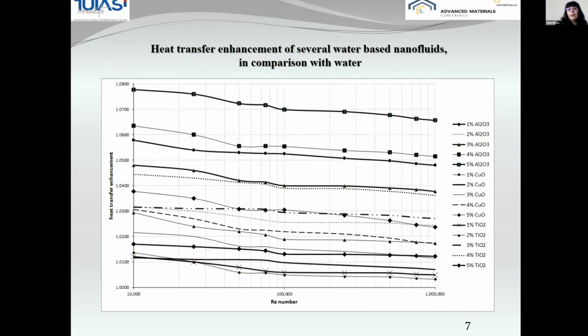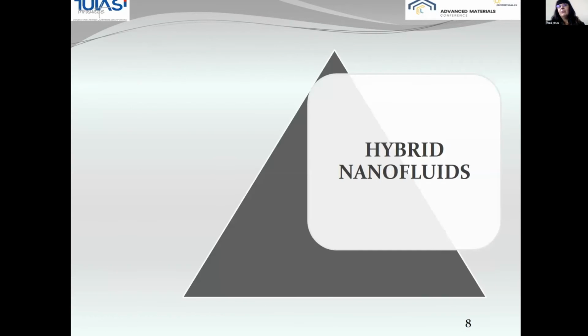Of course, in laminar convection, the enhancement is larger than that, because there the thermal conductivity is much more important. But adding nanoparticles to a regular base fluid increases the thermal conductivity, but it also increases the viscosity. So we have to balance the advantages and drawbacks of each case, and also the stability is very important. But I will move forward to a little bit about hybrid nanofluids.